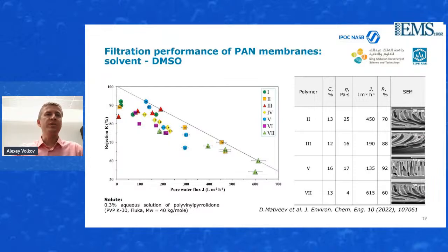And when we just plotted all of the data, that's for the DMSO rejection versus pure water flux, we can find that possibly 4 or 5 compositions are just nearby that upper bound, and that's quite interesting data, because it shows that by selecting the proper polymer sample, we can vary the water flux from 135 up to 600 something, with the rejection of the PVP, so there's like 40 kilogram per mole, from 70 to 92.